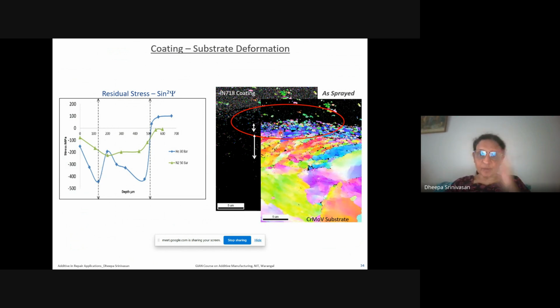Sometimes a cold spray process, while it works really well for lighter alloys and metals, can completely recrystallize and cause some severe plastic deformation into the steel substrate, so much so that the substrate can alter the microstructure or the texture, and it can lead to premature failure despite having the compressive stresses.